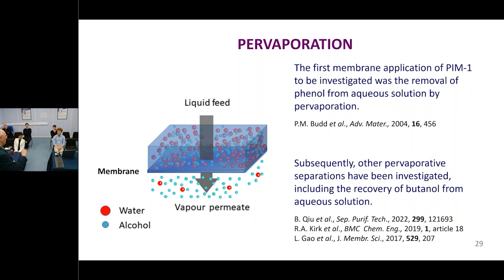Hydrophilic pervaporation is used at the moment in the processes for making absolute alcohol as part of the process, because it can be used to break an azeotrope. What's much rarer is something which will pull an alcohol out of water. You know, after some waters you can mix them, separating them is much harder, and that's the basis of what we're trying to do. But this is one of the relatively few polymers which you can take a dilute solution of alcohol, and then enrich it in the alcohol. In fact, we first looked at removing phenol from water. And later on, we looked quite a lot, for example, at butanol, with interest in biobutanol recovery after the fermentation process. So that's one of the ways in which we're looking at using these types of materials.